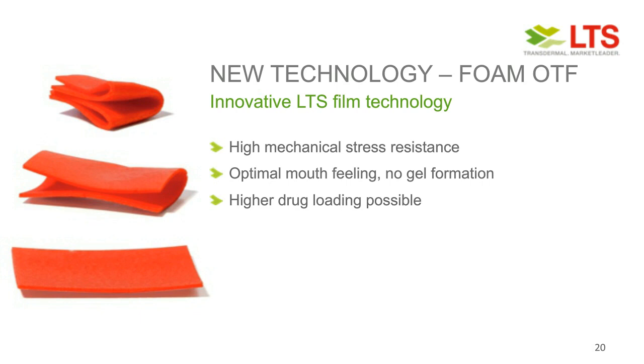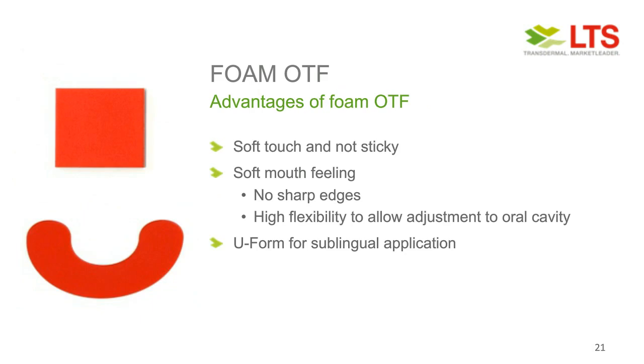Also, due to the properties of the foam OTF, we can achieve a higher drug loading compared to other very thin, just polymer films. So the key advantages of the foam OTFs are really the soft touch, the soft feeling. They are not sticky, so it really has a different feeling, and basically they melt in your mouth and not in your hand. They have a very soft mouth feeling. There are no sharp edges, so even with a square foam OTF you're not damaging your oral cavity, the mouth, like with some other OTFs, which really feel like a plastic film, so to say.